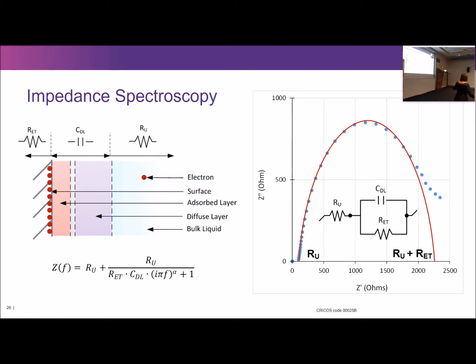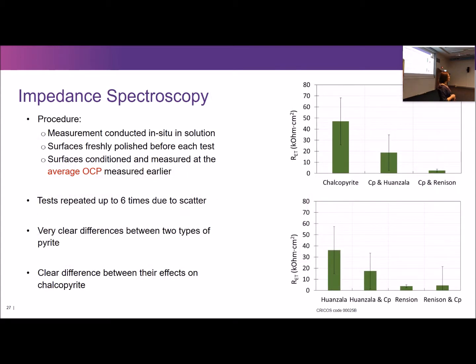You have to kind of cop the fact that your system is the system. You model it from first principles, and if it doesn't fit your data, you do more repeats and you cop the high error bars. It's just kind of how it is. So, this is why I have high error bars on my data. So what I did is I conducted the in situ measurements in solution. The surfaces, once again, were freshly polished each time, and the surfaces were conditioned at the same open circuit potential that I measured earlier as the rest potential. So things were always kept consistent.